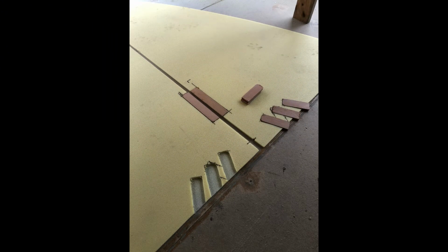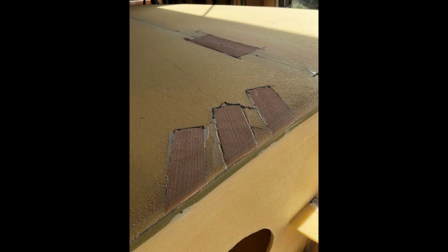These pics show where your cleats and mast go, and so you've got to work that out and replace the foam with wood or ply before you glass the deck. Where the chain plates come through the deck, it's a good idea to dig out the foam and replace it with some high strength glue or some filler mixed up with chopped off short bits of fiberglass. So you've got really good compressive strength there, because the chain plates are trying to pull the deck in and they will start to drag it in over time if it hasn't got good compressive strength there.